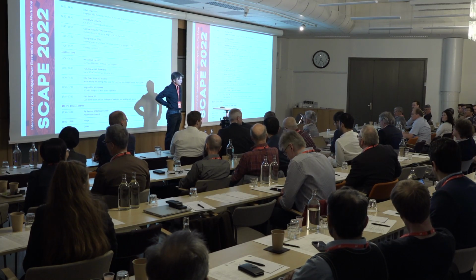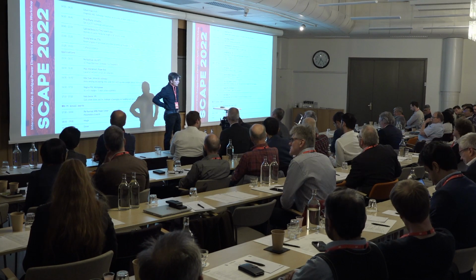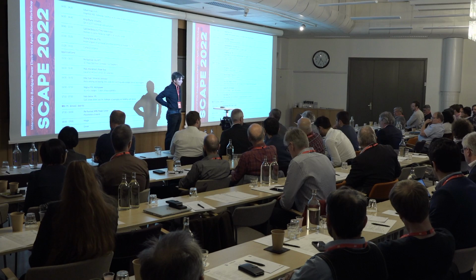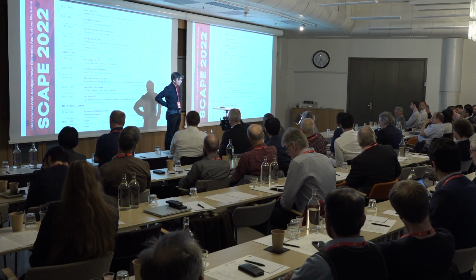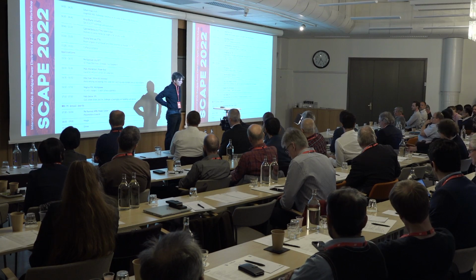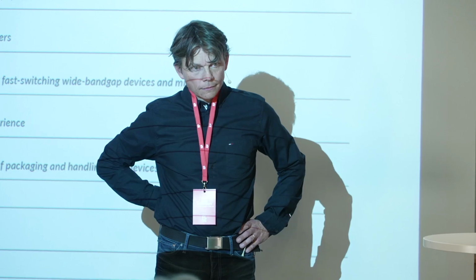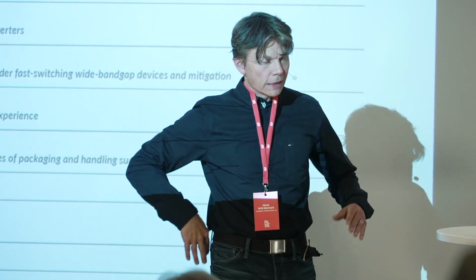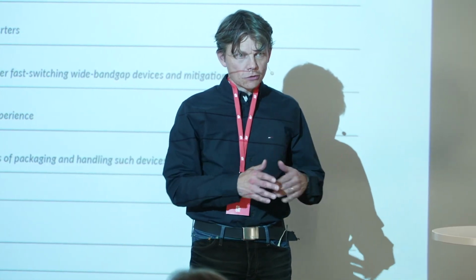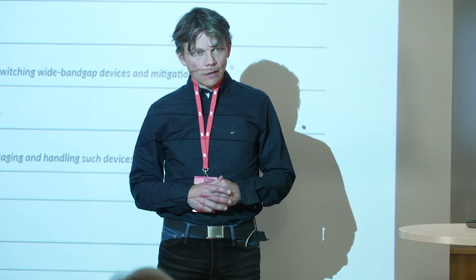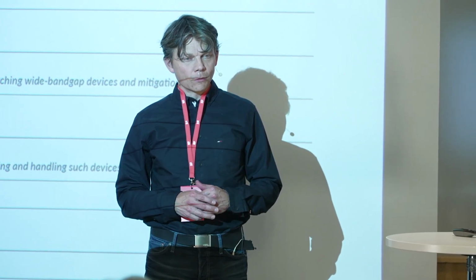I noticed that you didn't mention gallium nitride, which would be natural to compare with silicon at those low voltage levels. Then I think that you didn't find low voltage MOSFETs in silicon carbide. It depends on the resistivity in the substrates, such that there is probably no point in doing lower voltage MOSFETs because you don't gain so much in on-resistance anymore. Yeah, this presentation was a little bit in the direction of silicon carbide. Of course, we also follow what's going on in GaN, and maybe we can come back next year or in 2 years to present that. So, any additional questions?